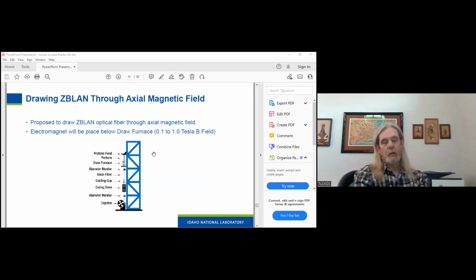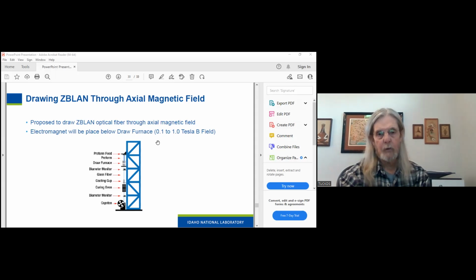Another idea is to propose to draw a ZBLAN optical fiber through an axial magnetic field. And this is just what a typical draw tower looks like, with a preform feed, your preform, a draw furnace, a fiber diameter monitor, coating cup, coating oven, a diameter monitor, and a capstan or a take-up reel. And the electromagnet would be placed just below the draw furnace. And I have designed a magnet that's variable between 0.1 and 1 Tesla. So we could test those and see what kind of attenuation coefficients we get out of it.